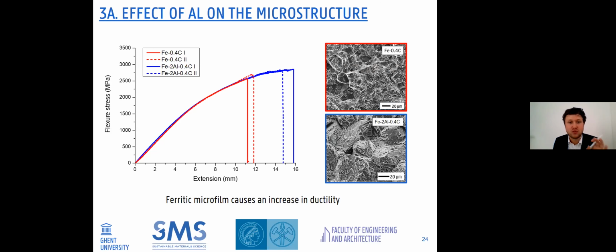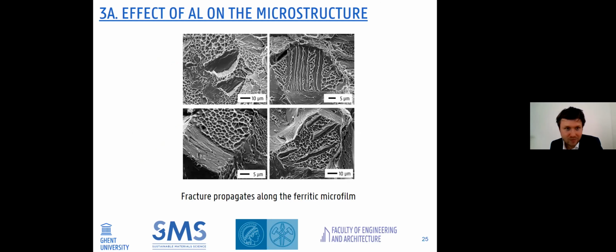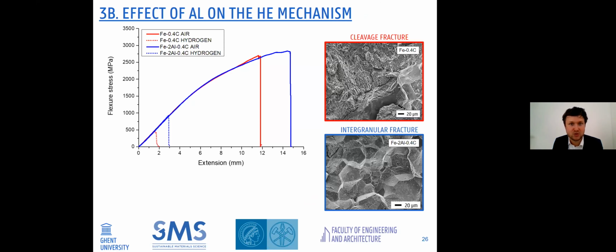If we now take a very close look at the fracture surface, we can see these microvoids. You can see the presence of very small microvoids which are dispersed over the underlying martensitic microstructure. So underneath the microvoids, you can see the martensitic microstructure, and on top of them, you have a very fine film of ferrite that transforms in a ductile way, and that acts as a glue in between the martensitic grains. For ductile materials, the presence of such a ferritic microfilm is quite harmful since it lowers the strength as well. But for brittle materials, the gain in ductility is paired with also the possibility to reach a higher fracture strength. So it's positive.